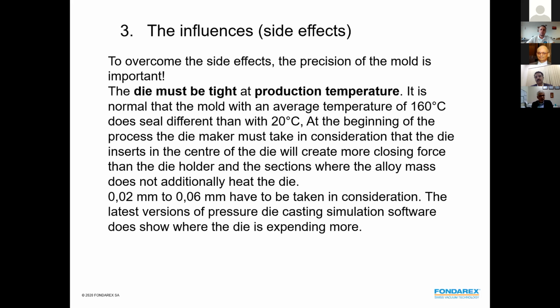The problem is often, or maybe it was in recent years, often the dies were precise at 20 degrees Celsius in the tool room. But for vacuum die casting, the die should be tight at 160 degrees. Or let's say the inside of the die is maybe 160. The frame, the die holder, is maybe 70, 80 degrees, depending on the size and depending on the environment. So basically the die must be tight in hot conditions. Therefore, if we measure a die, we should give to the outside 0.02 millimeters up to 0.06 more to compensate once the die gets hot.